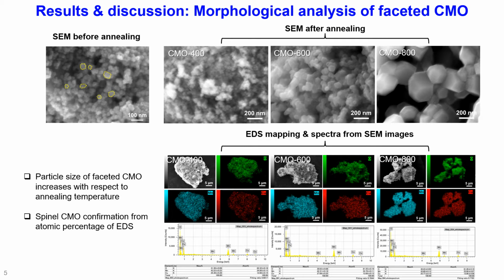Morphological analysis of faceted CMO. Here I have shown the SEM images of CMO before and after annealing. Before annealing, we could clearly see that there is some aggregation and very small particles formed, and we cannot see the clear faceted morphology due to the agglomeration. After annealing, the SEM shows the clear faceted morphology.